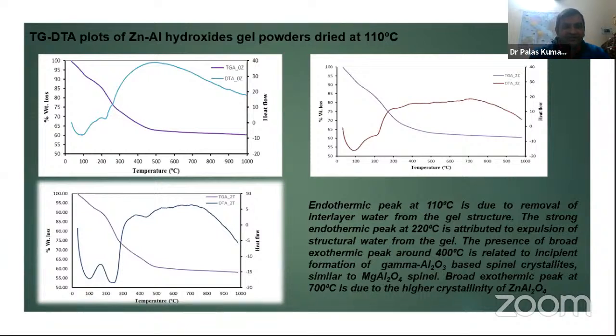And the most important thing is that there is an exothermic peak centered around 400 degrees centigrade, which is related to the formation of gamma alumina kind of spinel. Especially for 2T and 2Z, that is the 2% doped titanium and 2% doped zirconia, there is a broad peak centered around 700 degrees centigrade, which correlates basically to a higher crystallinity of zinc aluminate spinel, which is evidenced from other studies like FTIR and XRD coming later.